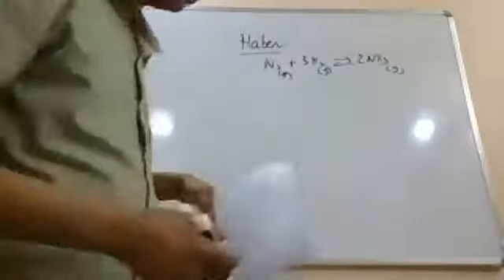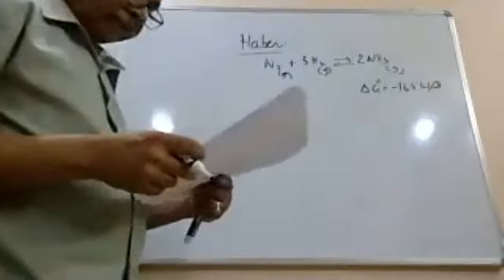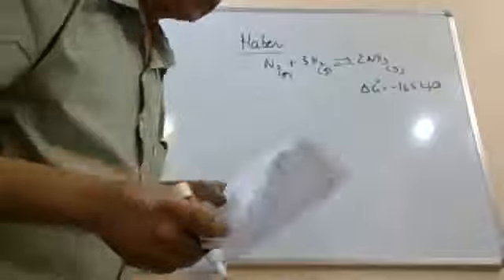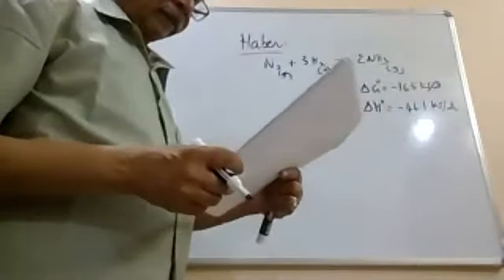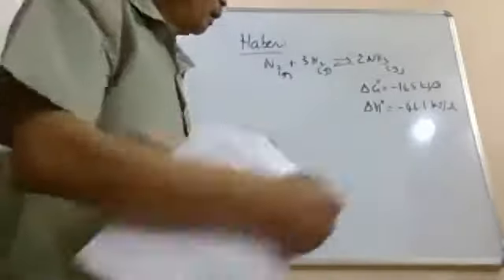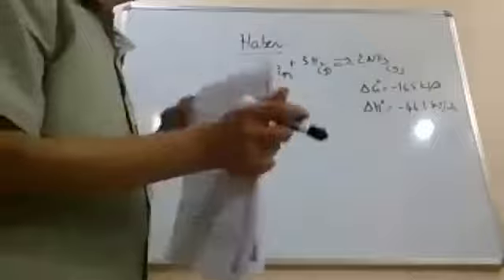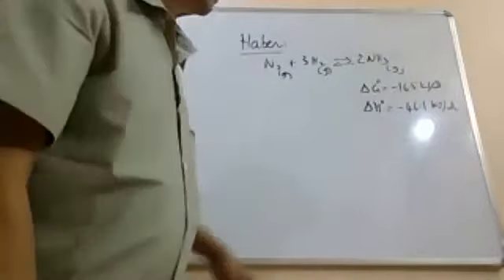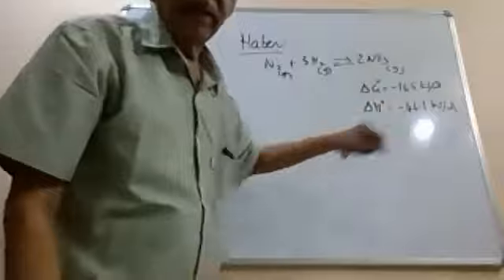All right. So if you look at the various thermodynamic parameters for this, the free energy change is about negative 16.5 kilojoules per mole. It's an exergonic process. And the delta H for this process is about negative 46.1 kilojoules per mole. So if we now look at these processes, clearly the reaction is spontaneous because delta G is negative, right? And now if you look at the delta H, it is exothermic.